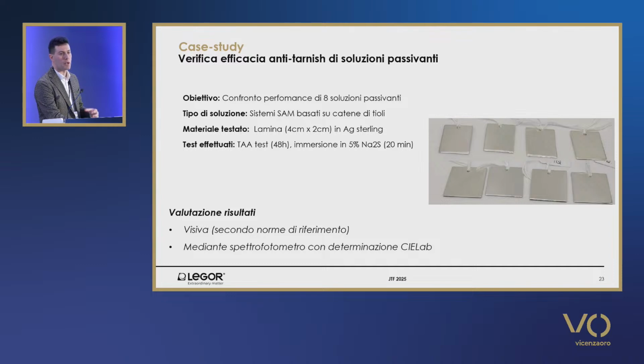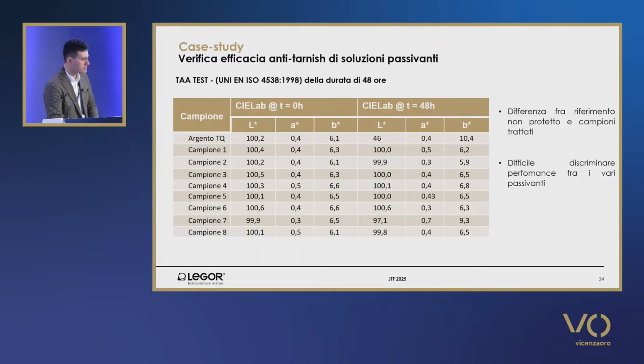Now, I'd like to show you the results of this study that we carried out at Legor with the objective of comparing 8 passivating solutions taken from the market, all based on SAM systems. Different sterling silver layers were tested, and we did TAA tests and immersions in 5% sodium sulfide solutions for 20 minutes. Results were assessed in a visual way, but a more objective evaluation was made with the use of a spectrophotometer.